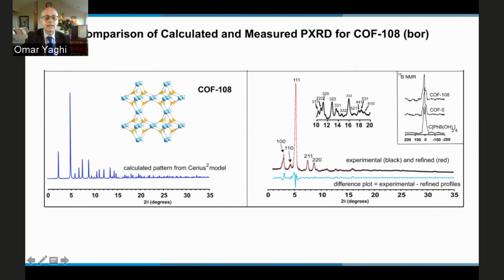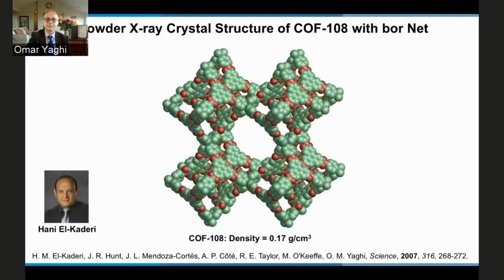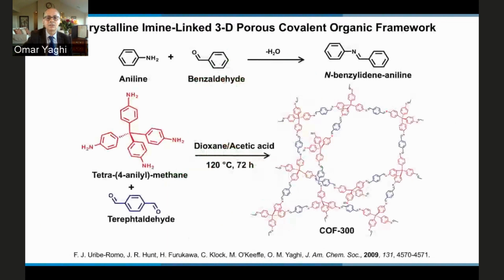This is the calculated X-ray powder diffraction. This is the experimental one that we can obtain the structure from. So that's 2D and 3D covalent organic frameworks, and this set off, of course, a worldwide activity in racing to make other COFs from other linkages, such as in our case, we extended this chemistry to imine linkages. And here you see we got rid of the water and added acetic acid so that we can enhance the reversibility of this reaction during formation and get crystals.